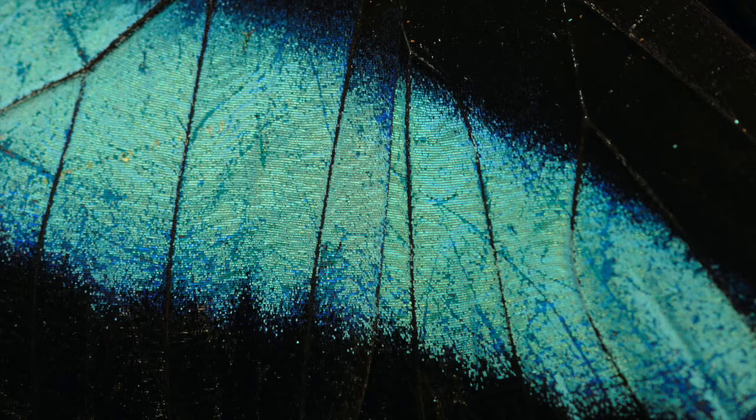So in such a case, let's say in a soap film or in a tiny thin film of oil on a puddle of water, or on a thin film of protein on the surface of an animal, the colour which is reflected explicitly depends on the material and on the thickness of the film. So in the case of the Morpho Butterfly, for example, we don't just have one layer, as we see is responsible for the colour in soap films. We have multiple layers stacked on top of each other. And it's the combined effect of all of those layers inducing constructive interference, bright reflection for blue, that gives rise to the intense, brilliant, iridescent blue reflection on Morpho's wing scales.